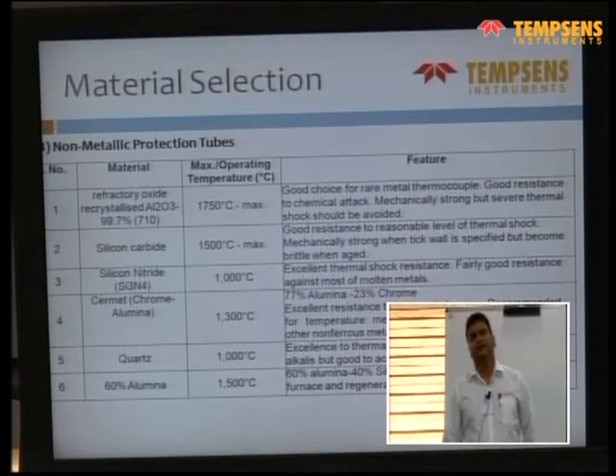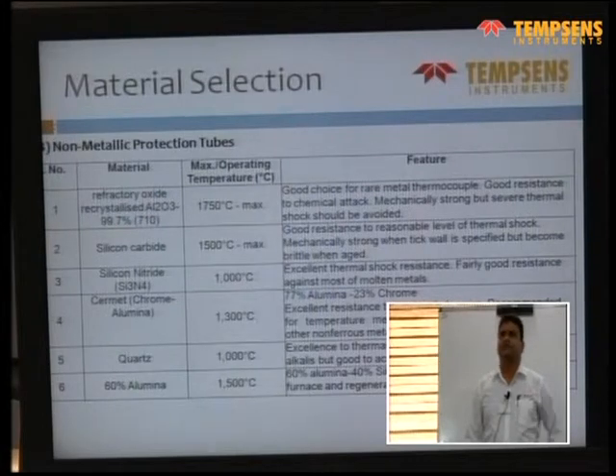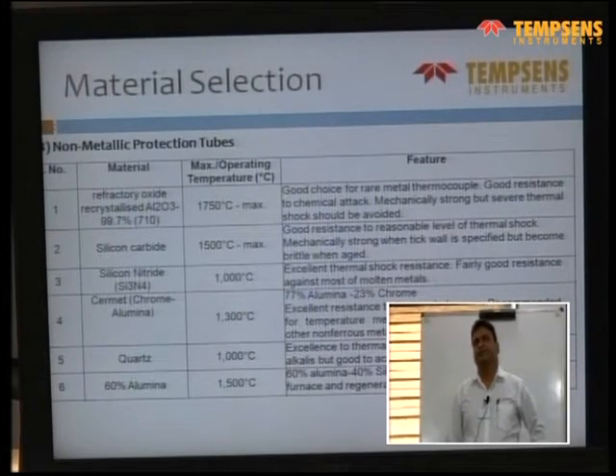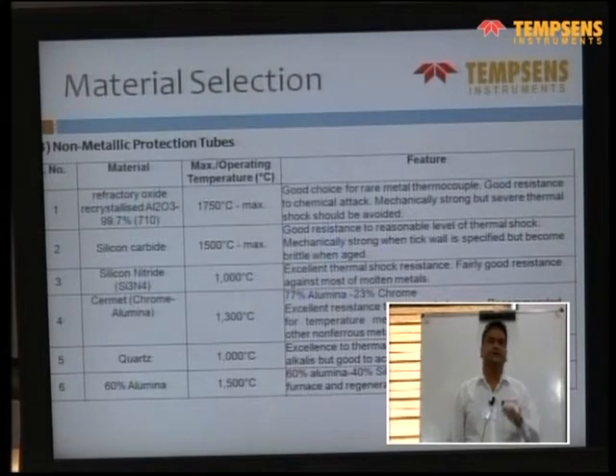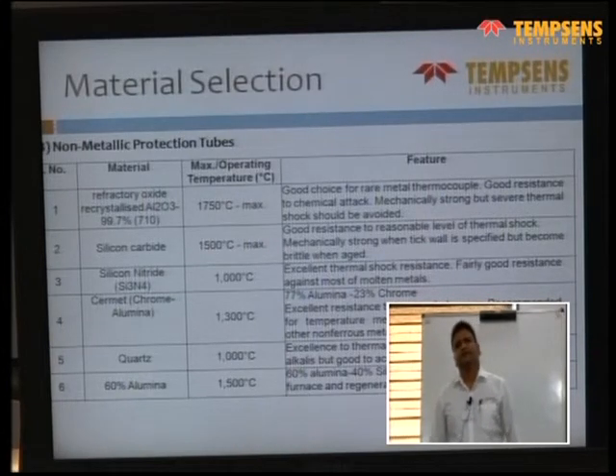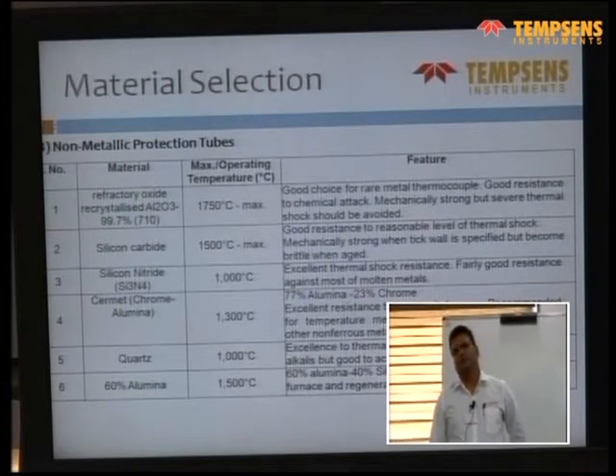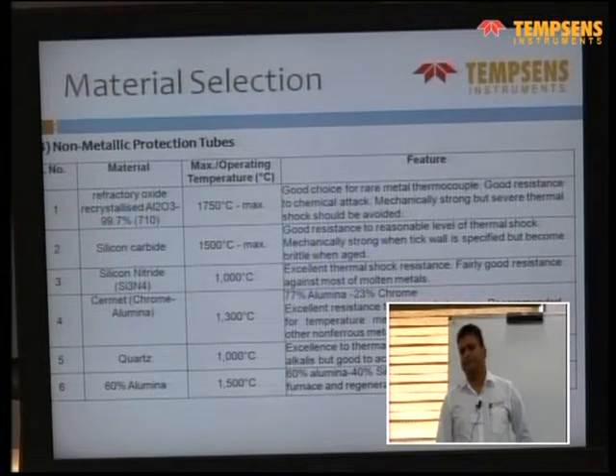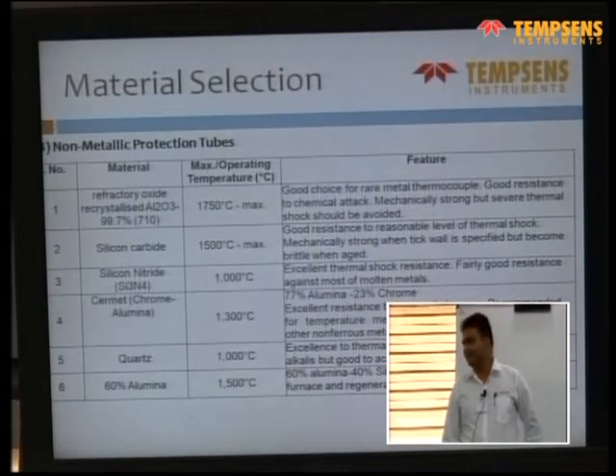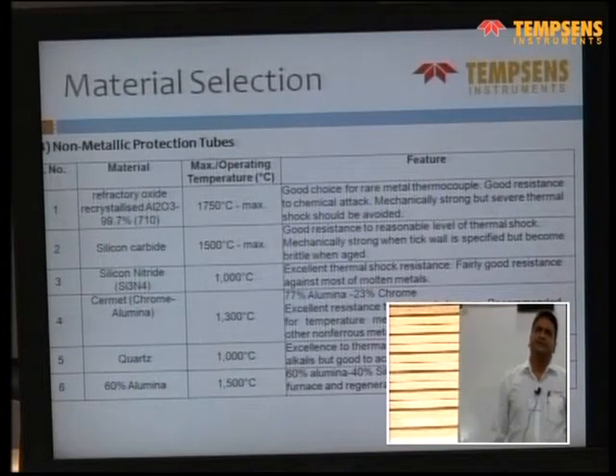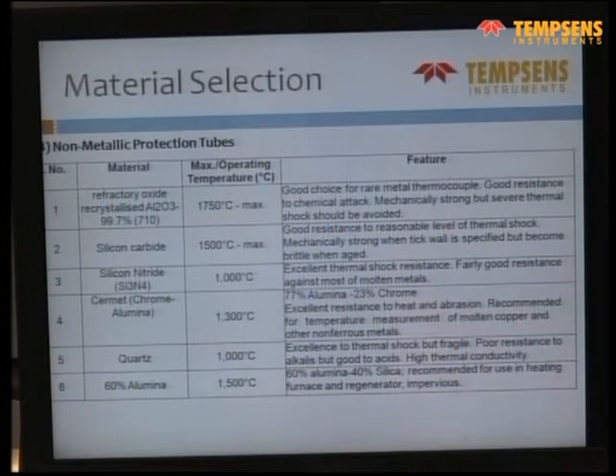Then silicon carbide, it has good temperature resistance up to 1500 and good thermal shock resistance. So this is also used in combination, inside can be an alumina tube and outside can be a silicon carbide tube for better thermal shock resistance. Then silicon nitride or Sialon, so this is used for molten aluminum application, and this tube is non-wetting with molten aluminum. Then Cermet is again for high temperature. It is a metal ceramic, and it has 77% alumina and 23% chrome. This is used for molten brass application, or even for molten copper application this is used.